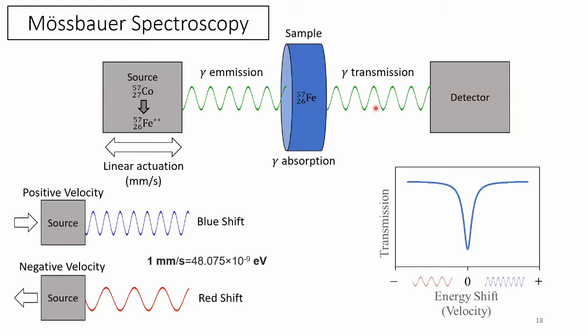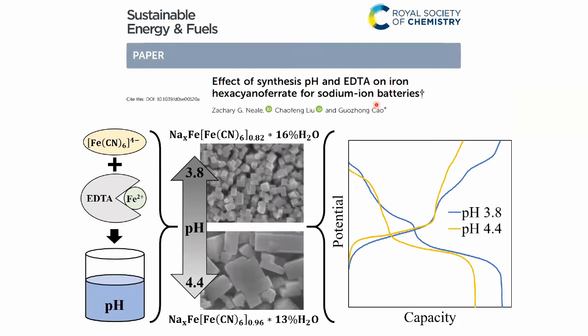Okay. So an example of using this method comes from a paper, and I'm kind of self-advertising here. This is my own paper that I recently published. This paper looks at how the synthesis of this material, iron hexacyanoferrate, is affected by pH and this organic molecule called EDTA, ethylenediaminetetraacetic acid. And this molecule is a chelating agent. And chelating agent means that it will bind to the iron in solution in multiple ways. So essentially, in this synthesis, I'm controlling the pH, which will control the chelation strength of EDTA to the iron. And that will affect the morphology and also the chemistry of the sample, which will in turn affect the electrochemical performance of it as a sodium ion battery.